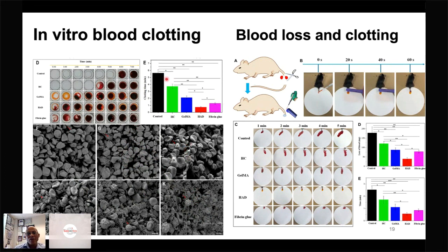Then we took this in vitro data, and then we did a blood loss and a clotting assay, and you can see that we were able to demonstrate in a rat tail amputation model that the amount of blood that is lost was minimal for the hemostatic adhesive that we have developed, as opposed to the control or the enzyme alone without the gelatin methacrylate matrix. And it was also much lower compared to the fibrin glue, which is of course what we want.